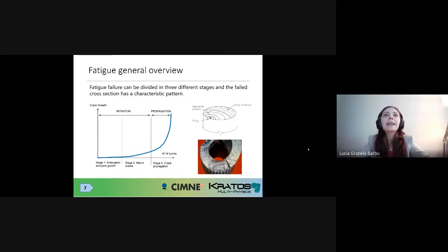Okay, now regarding failure due to fatigue, let's just say that there is a characteristic pattern when you see a fatigue failure surface. Basically, fatigue initiates at an origin, which is generally found close to a defect in the internal structure of the material. It can be a large pore, it can be an inclusion, etc. Then you have an area where the crack, which has initiated at that defect, propagates, where you can see this clamshell pattern. And in the end, when the crack has propagated throughout the cross section until it reduces this cross section to such a small level that it can no longer bear the load, then you have a final fracture which is quite brittle.